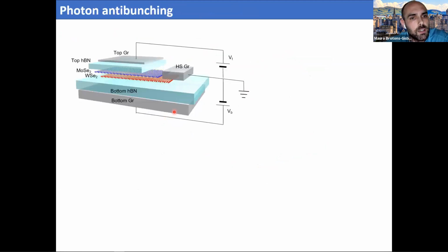And for that, we fabricated a device that looked like this. Basically, we had our Moiré superlattice, created by these two materials, encapsulated between two hexagonal boron nitride layers again. And then we finished the device by adding a top graphene and a bottom graphene layer that we used to apply vertical electric fields, as we'll see later.